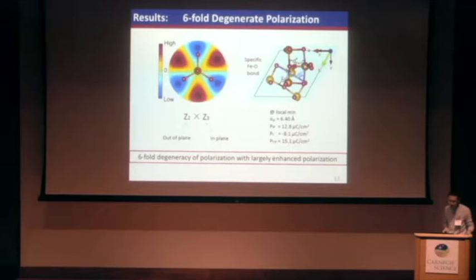This phase has a quite novel polarization. Yeah, we know it has out-of-plane up and down polarization, but here we also notice that since one of the iron-oxygen bonds will break, it has three choices. Each bond breaking can lead to a different in-plane polarization state. So totally there are 6-fold degeneracy of polarization in this P1 phase. And also for the polarization, besides the out-of-plane one, there is an even larger in-plane one that emerges, resulting in a quite large total polarization, which is almost twice that of the hexagonal phase.